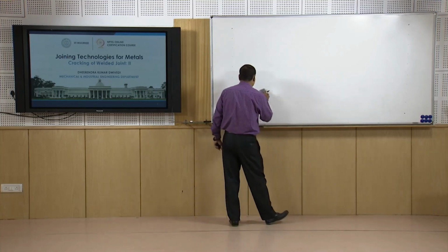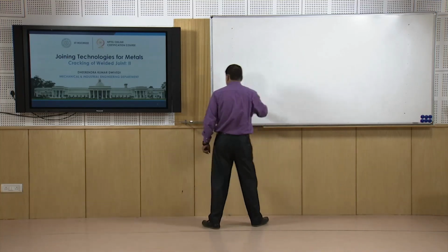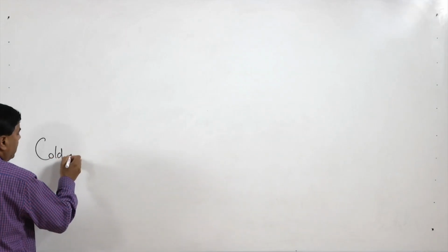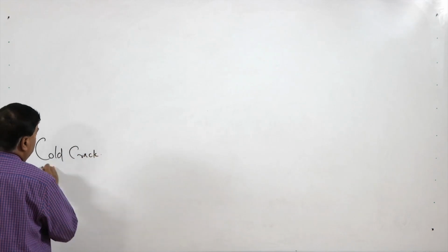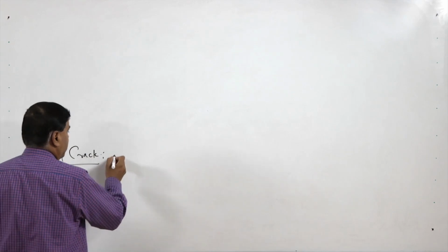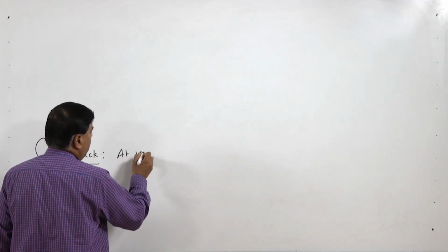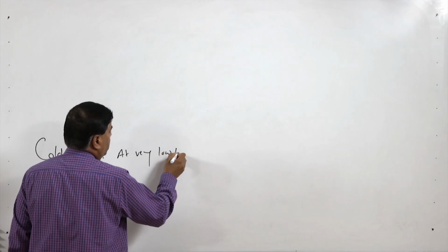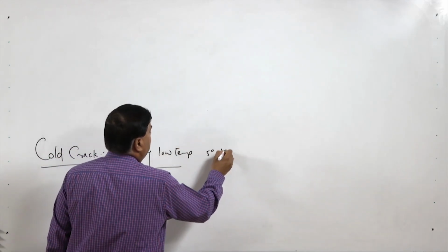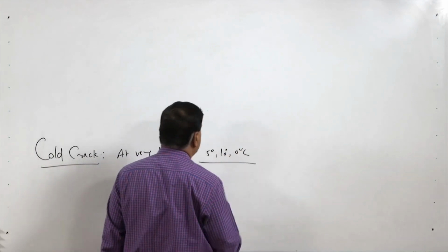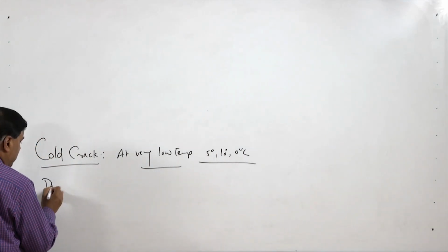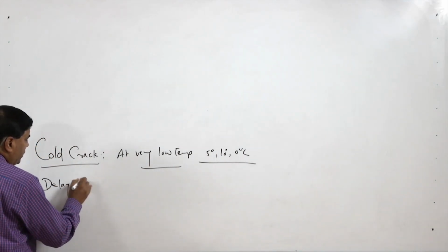Another one is the cold crack or the delayed crack, various names which have been given, very commonly known as cold crack. This type of cracking is called cold crack because it occurs normally at very low temperature conditions, like maybe 5 degrees or 10 degrees or 0 degrees centigrade. So, under low temperature conditions, this kind of cracking tendency is observed. Delayed cracking is called so